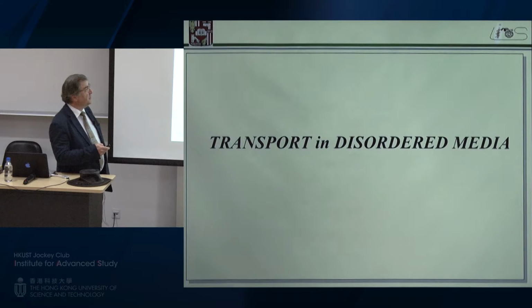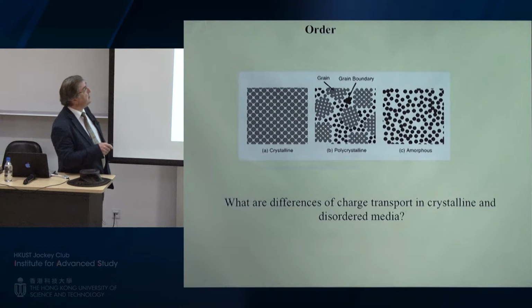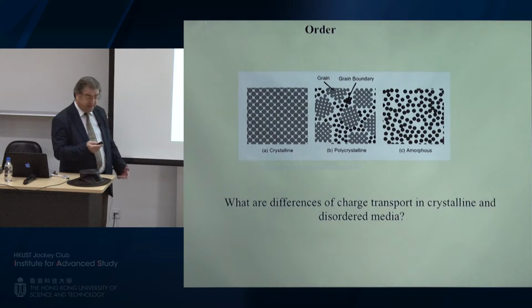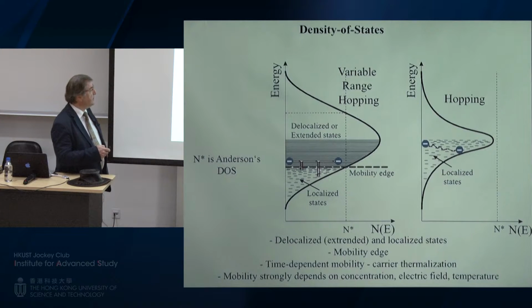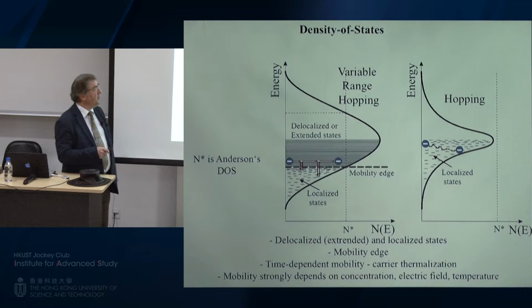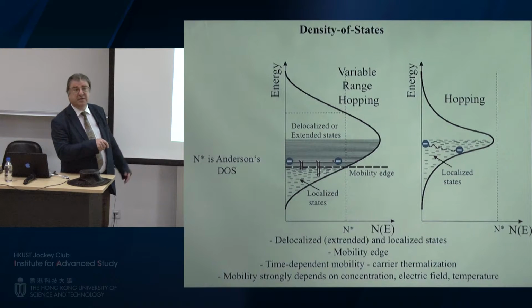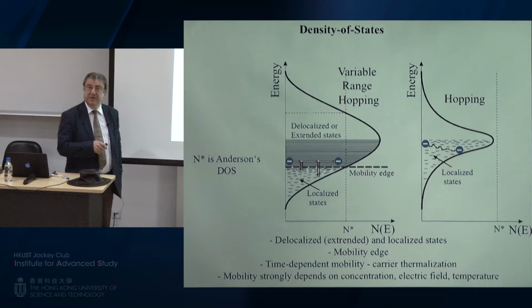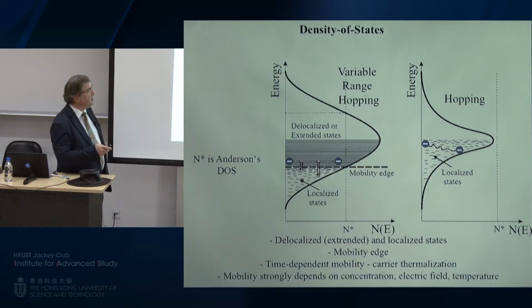and this is indeed the transport in disordered media. If you have order, crystalline or amorphous or polycrystalline, there is a difference in the charge transport properties of the system. And actually, Mott and Anderson got the Nobel Prize for this. If you have a system which has heavy disorder, the energy states which are below some mobility edge are localized states. So the charge carrier can only hop between the states. Only above this mobility edge do you have, let's say, metallic or ballistic transport.